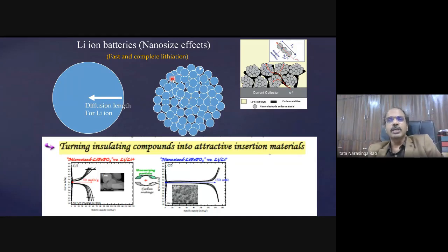But you can ask, how is the current taken out? When the electron comes to the surface very quickly as the lithium goes, and these particles are coated with carbon, and carbon is electrically conducting, you have the current collector. So you have to coat these materials in the form of a thin film with carbon incorporated into it. And then whenever there is lithiation and delithiation, the electrons go to the current collector. And that is coming through your cell and through the external circuit, and your electric motor will run.